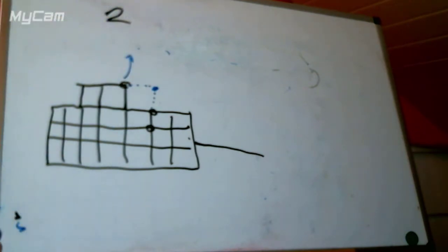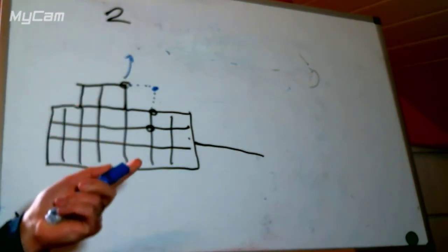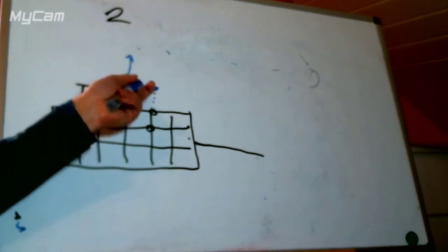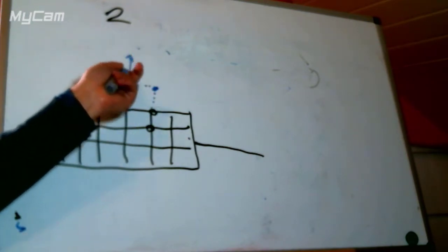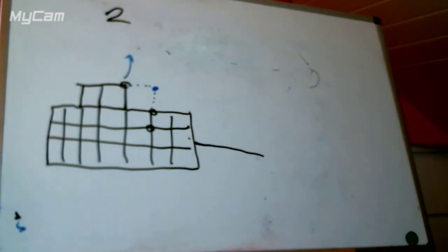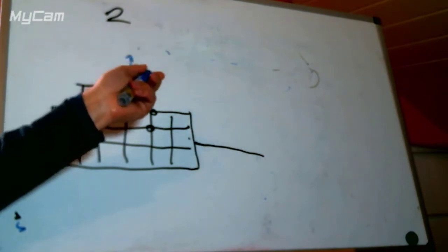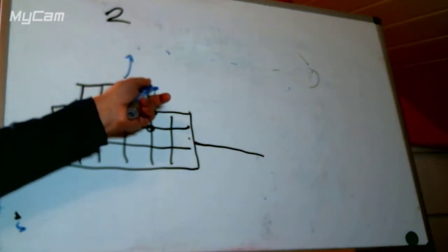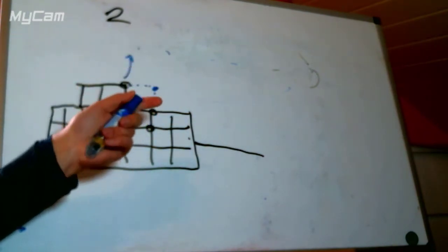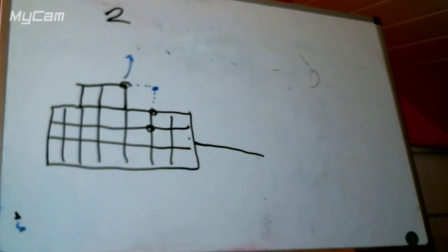And we can see that reasonably logically, the ones at the corners, on the outside corners, are more likely to dissolve because they can go in all directions and they are not attached to as many atoms. And the ones in the inside corners are relatively unlikely to dissolve, but they're the ones that a new one will tend to attach to. So it will tend to attach here because it's attached to more sites than starting a new center, just like we had in the gas phase.